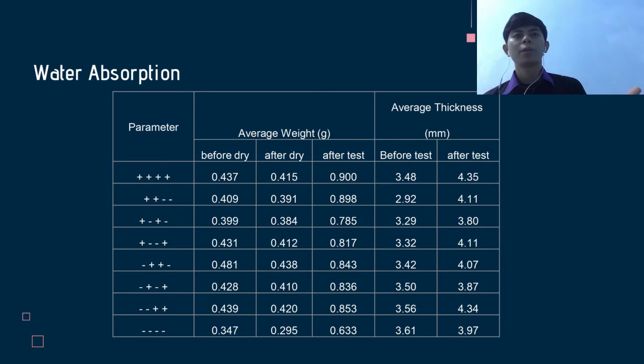So for the water absorption, this is the result for the water absorption. As we can see, we have 8 samples of the parameters, and then we have the average weight and the average thickness. For the maximum parameter, the weight after drying is 0.9, and the average thickness is 4.35 mm. Then for the minimum value after the test, the average weight is 0.633 gram, and the average thickness is 3.97 mm.